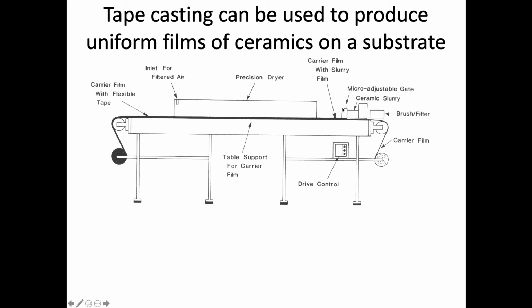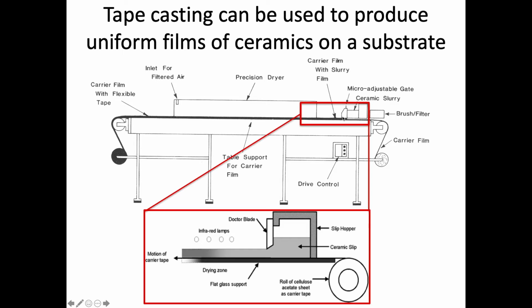And then here we have typically what's called a doctor blade. And so I think I've got an image of it here. Yeah. So we have the slip inside this chamber. And then we have what's called a doctor blade. And so basically what this does is it can be adjusted in height to create that film at a specific thickness. So that controls the thickness of the ceramic. So basically this conveyor belt moves, and so the ceramic is in place, but the film itself moves at a given rate so that we create a thin film on that substrate of the ceramic.